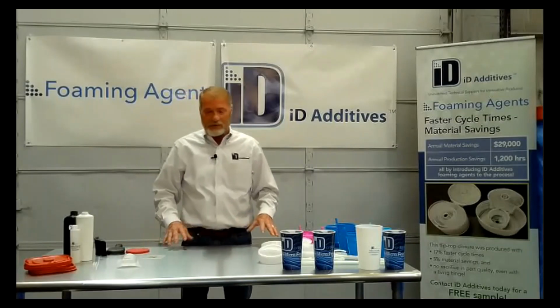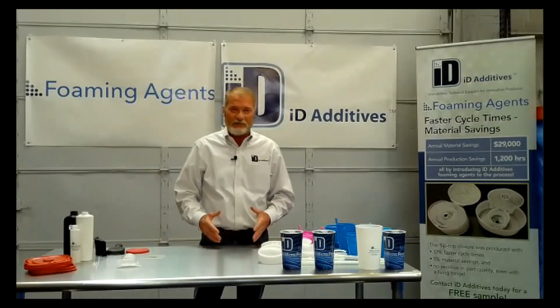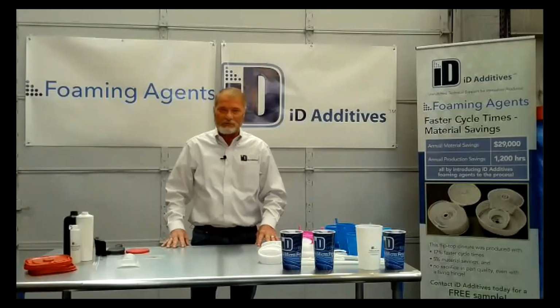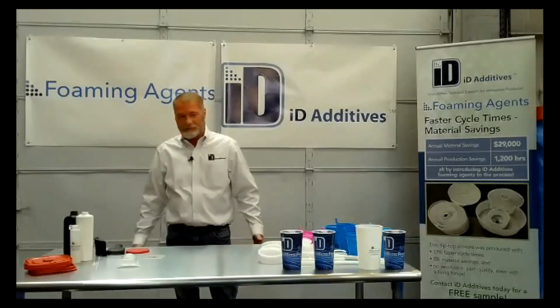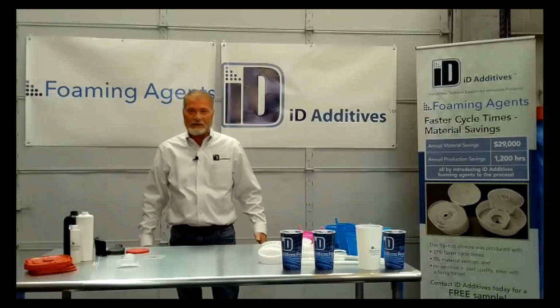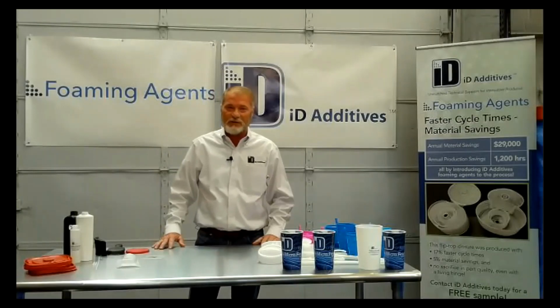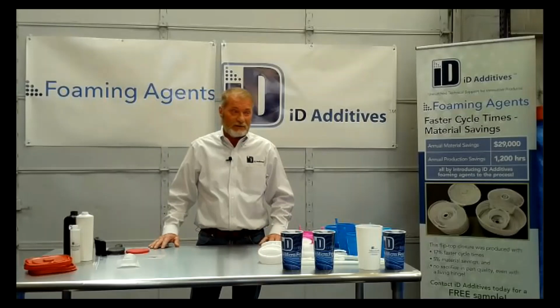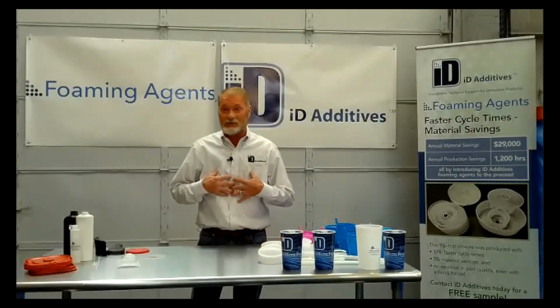Most of the endothermics go off about 330, 320, right in there for olefins, styrenes, PVC, ethylenes, propylenes, TPEs, TPOs, TPUs. Acetal is a kind of a weird product, but exothermics work best in that application. I had to learn the hard way on that.